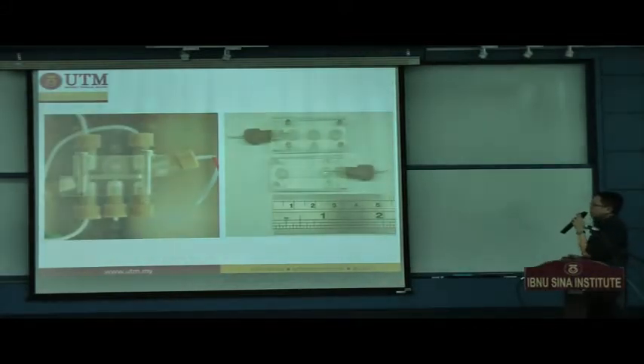So this is the extraction cell, which is actually pretty small. And you probably can't see very obviously that the membrane is already placed on the top. These PMMA plates clamp each other with the membrane at the interface, and the sample flows through continuously, and this one is going to the waste. And this is the acceptor solution positioned in your acceptor channel, but it remains stagnant during the extraction. And this is the electrode that we put directly into the chamber, directly from here all the way to the chamber, to provide the applied voltage.